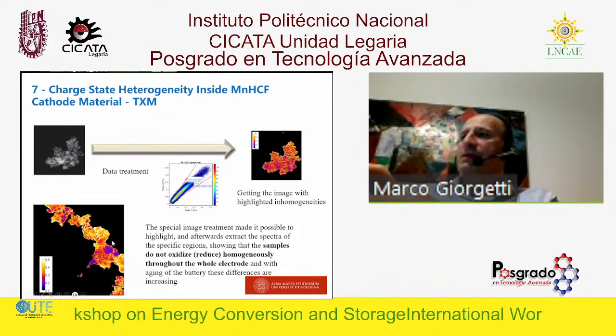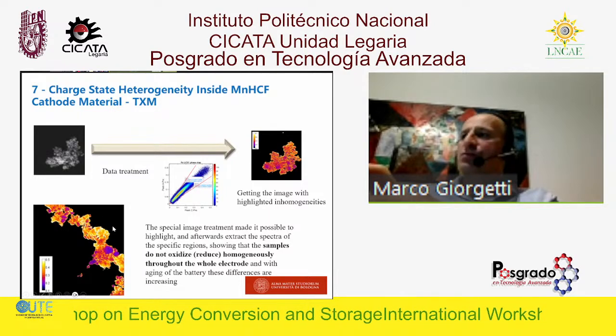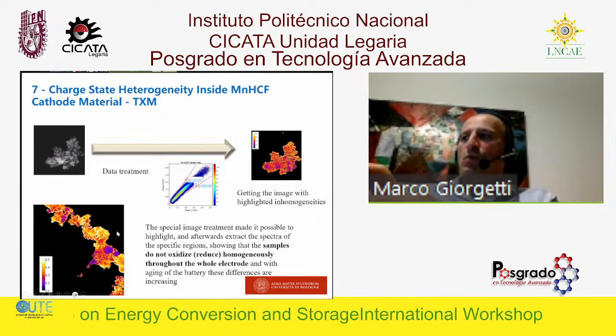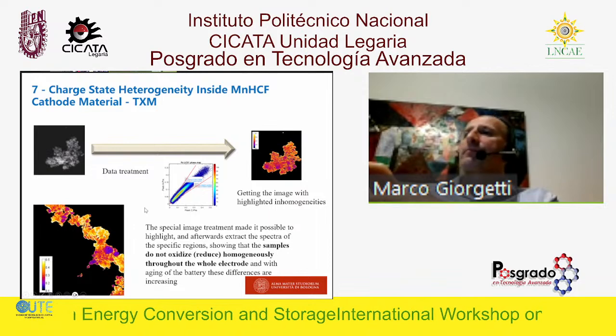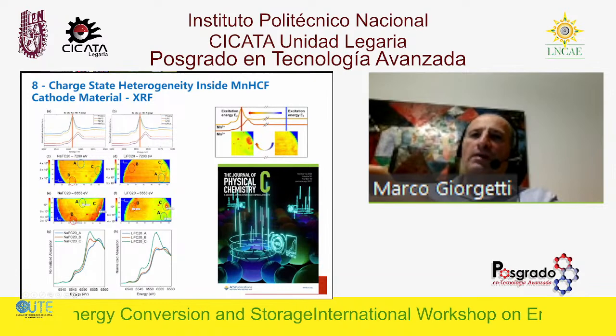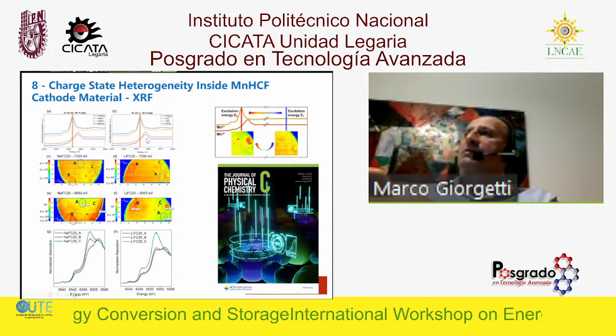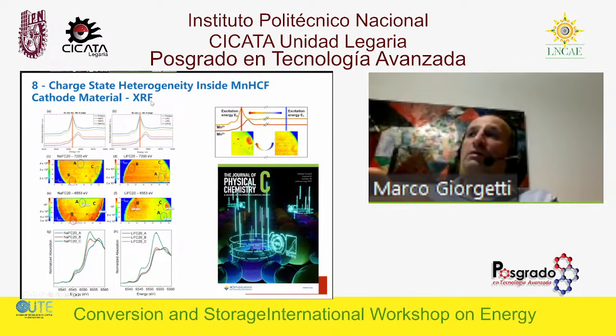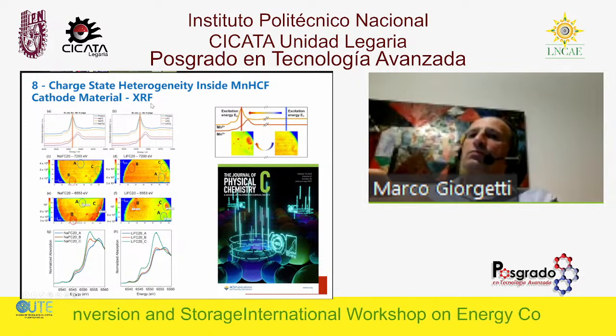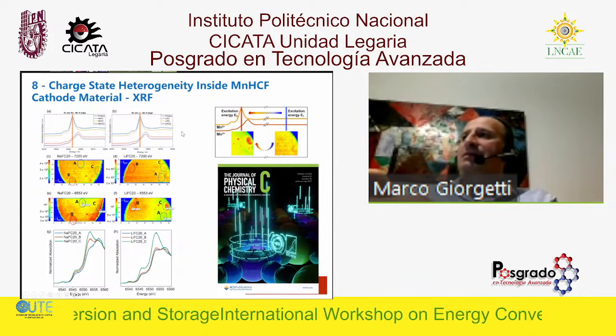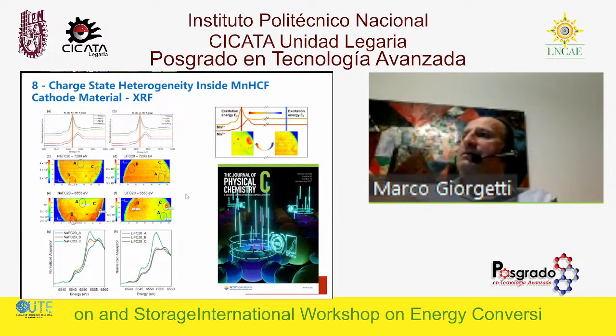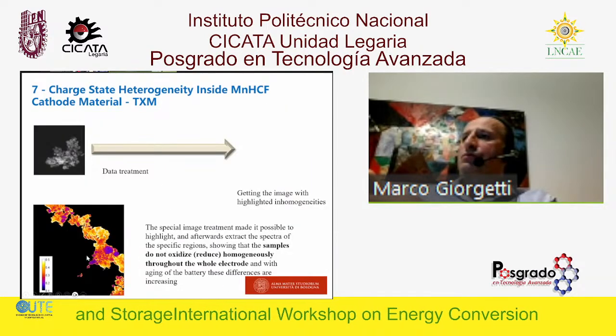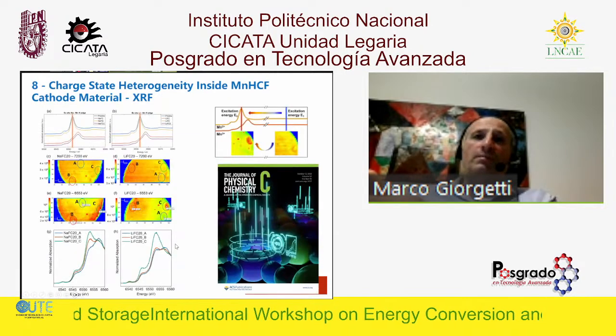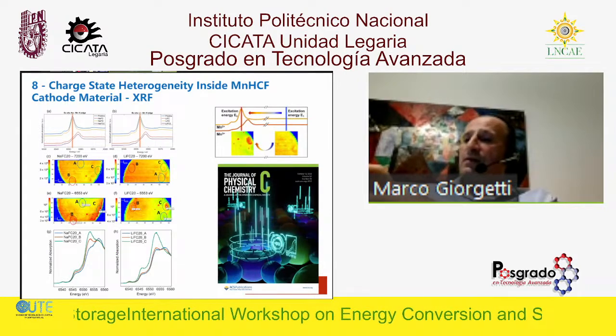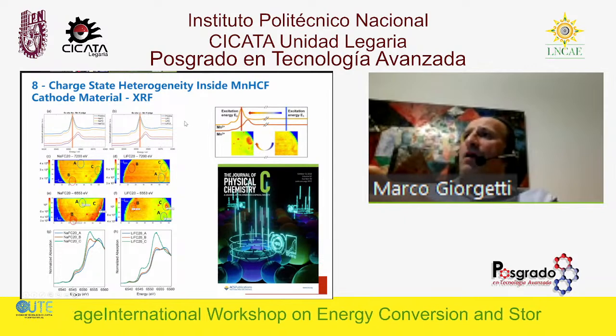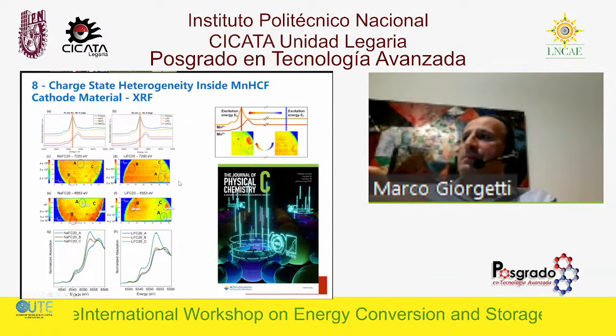And here it was possible to see that samples on aged electrodes do not oxidize or reduce homogeneously through the whole electrode, but there are differences. Another technique that is complementary in terms of spatial resolution is this one. You can conduct X-ray fluorescence spectroscopy with microscopy. And why do you want to do this? Because the sample representativity is, of course, better than in TXM. In TXM, you can have a very fine spatial resolution, as indicated, but you only probe a portion of the material, just a few drops that you put in. On the XRF, the positive is that the sample representativity is very high.